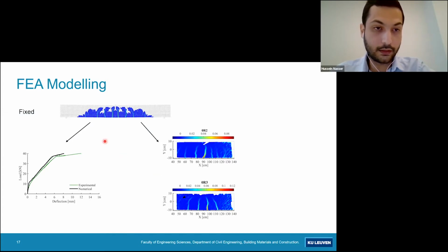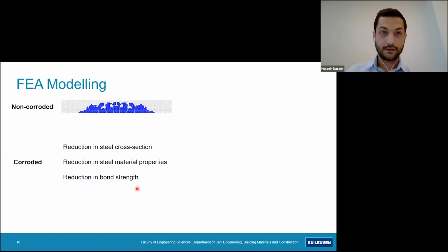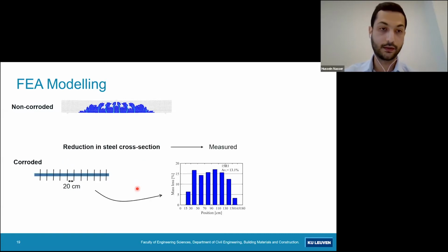The validation was done on the load deflection curves of the non-corroded beams. And the numerical cracking pattern was also compared to the cracking pattern obtained from DIC, which shows multiple cracks that are closely spaced. After validating the non-corroded beam, the corroded beams were modeled using reduction factors. The reduction will apply to the cross-section, the steel material properties, and the bond strength. In the following slides, I'll explain how these reduction factors, or damage models, let's call them, were chosen.